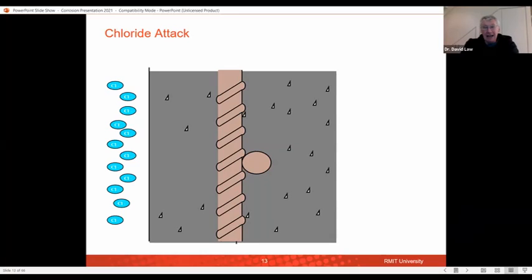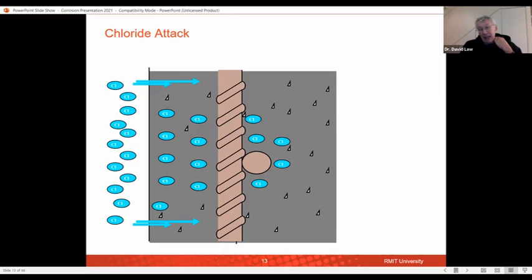So how does chloride get into our concrete? What happens? Well, our chloride may come from our de-icing salt or from the seawater, and it will slowly diffuse into our concrete. That is, it will come into the pore water that we have within our concrete, and it will diffuse under that concentration gradient of chloride ions until it reaches the steel bar. And once it reaches your steel bar, you will actually get corrosion initiated.